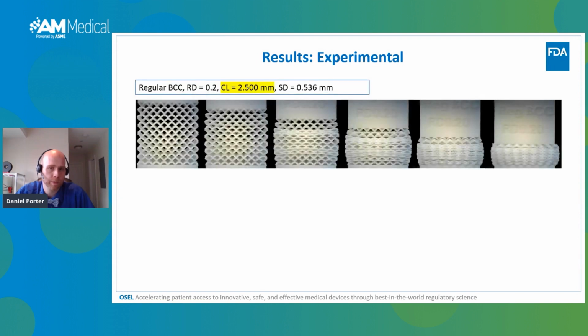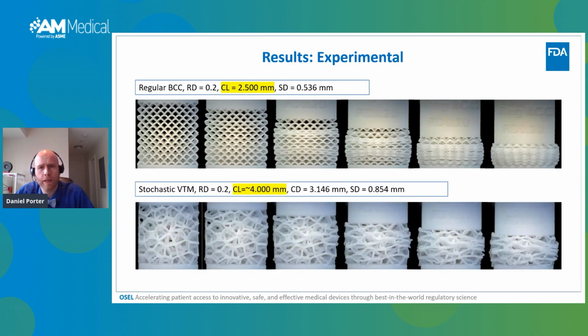Going into some experimental results, here's some time lapses of some of the samples as they're being loaded. This one is a compression sample with a BCC lattice. You'll notice that given the failure modality for this lattice, it's actually quite symmetric. But the Voronoi, due to its stochastic nature, the strut dimensions as they deform are not symmetric. And we're also looking into what kind of choices could symmetry be appropriate for an FEA for, say, lattice performance, because having symmetry in a model actually saves a lot of time in processing.